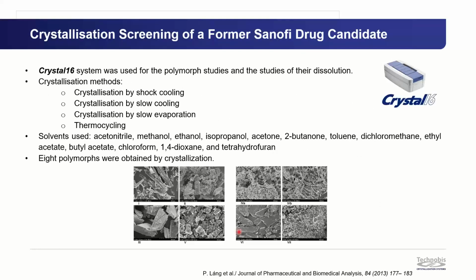Another consideration with polymorphism is from a legality standpoint. So this is a case of a former Sanofi drug candidate where they had conducted a polymorphism screen and identified 3 polymorphs. A generics company using the Crystal 16 conducted a polymorphism screen using shock cooling, fast and slow cooling, slow evaporation, and thermocycling with a range of different functionality solvents, including chlorides, acetates, nitriles, and alcohols. And from this, they were able to identify an additional 5 polymorphs, undermining the patent of Sanofi and being able to go direct to market.